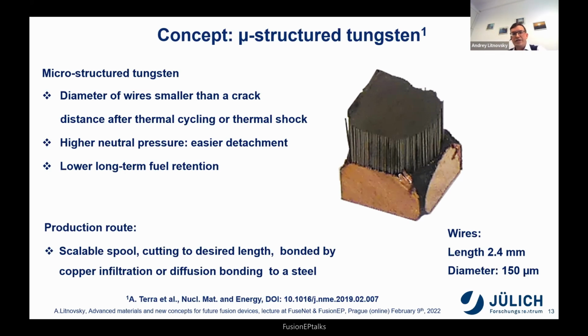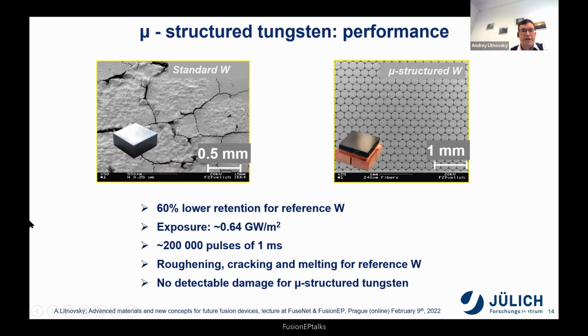The essential advantage of such a system is that the diameter of the fibers is smaller than the crack distance after thermal cycling or thermal shock. So it basically isolates damage within this small diameter of the fiber. It may provide high neutral pressure because plasma attaches on the larger surface, and may then provide a lower long-term retention. But let's see how it all works.